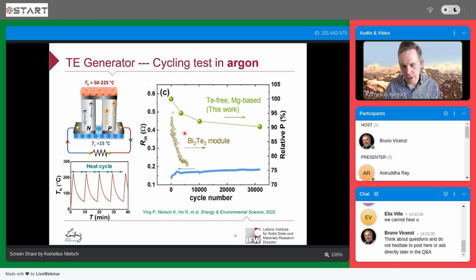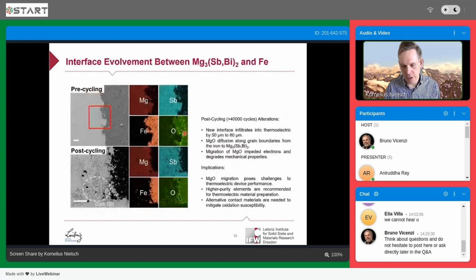These first tests were done directly under inert atmosphere in a glove box system. The goal was also to look at how it behaves outside, in a real environment like air. Before I come to the cycling test in air, I also want to shortly show some results where we investigated the interfaces between the contact material and the thermoelectric material before and after this testing. You can see some degradation of the device, but overall it keeps rather stable properties. The weakest part of the whole device is up to now the soldering material.